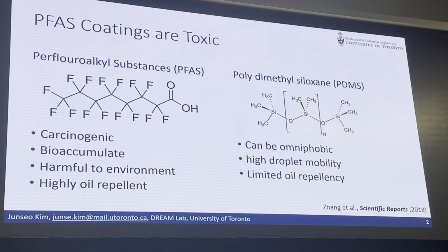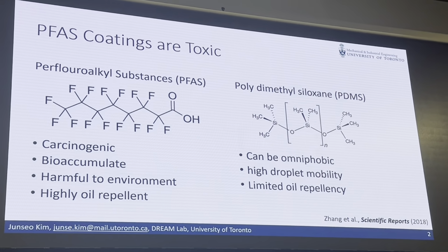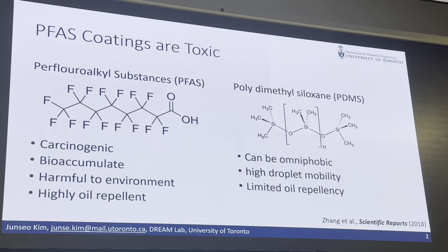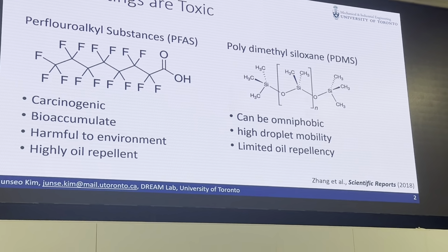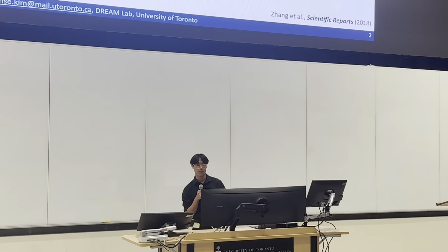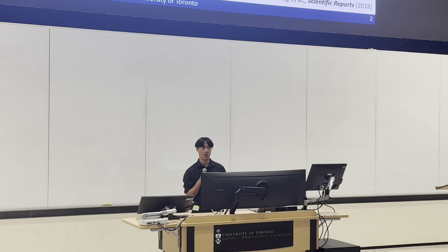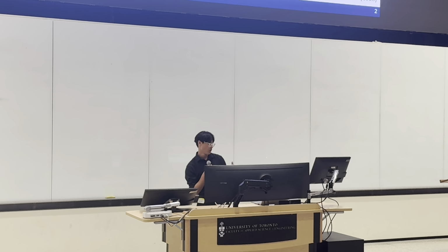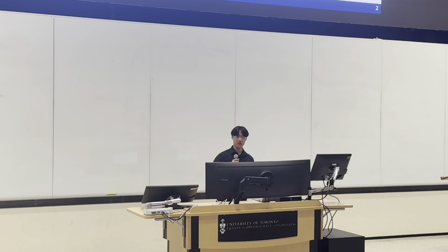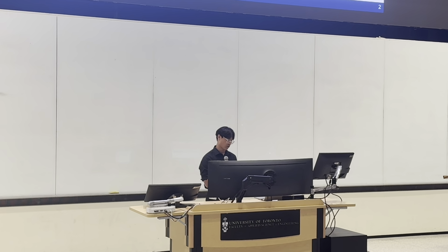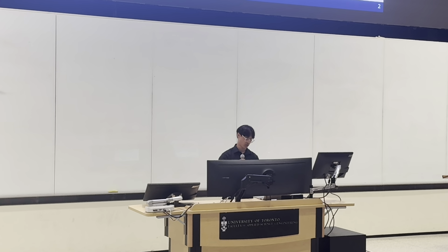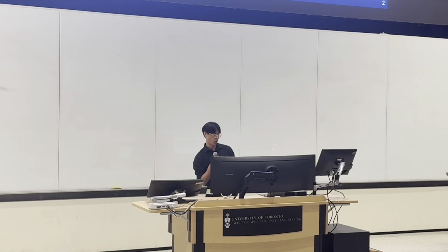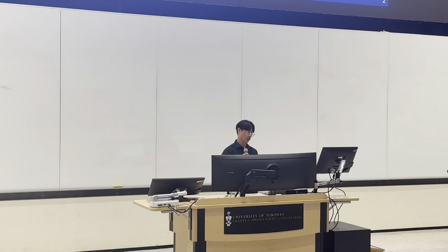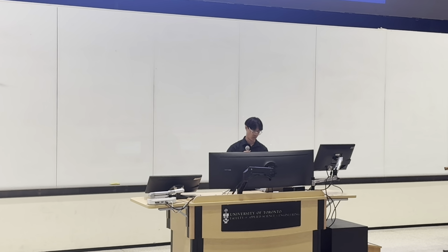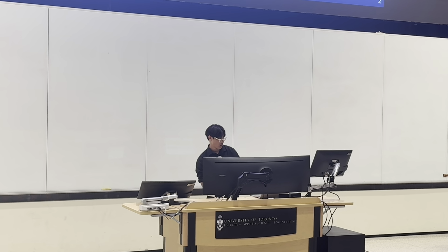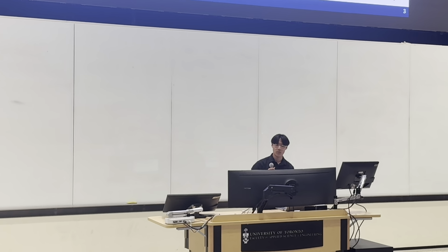And when they're formed in brush coatings, they repel most liquids, and they have high droplet mobility. So what that means is when droplets are deposited onto a brush coating made from PDMS, the droplet is easy to move. So that's a highly desirable characteristic of this coating. However, it's very limited in its oil repellency, which is why I was trying to improve that for my research this summer.